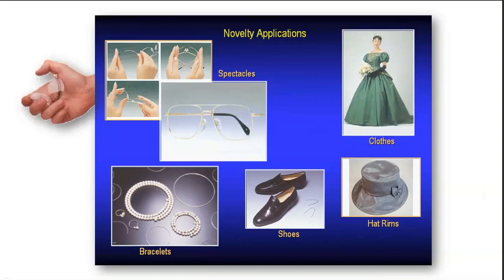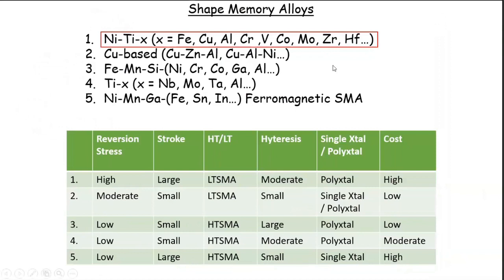But what I will do now is to give a picture of all the shape memory alloys. It's only a small list of them, but these are the most outstanding shape memory alloys which have either been put into some application or are very close to some application. Of course, I mentioned the nickel titanium shape memory alloy, and as given here, there are a lot of ternary additions. A reason I've already mentioned is that you try to reduce the transformation temperature. Of course, one can also try to increase the transformation temperature. They have been of interest, like zirconium and hafnium, which are added for that purpose.